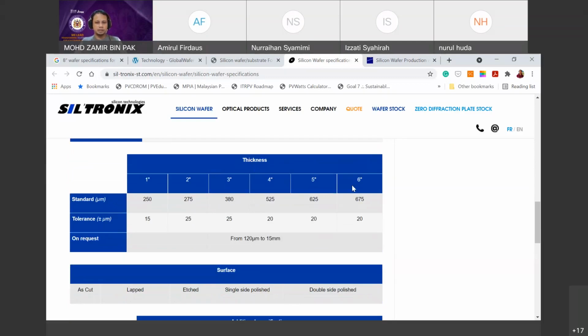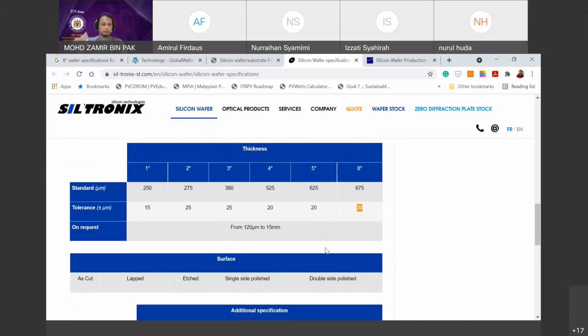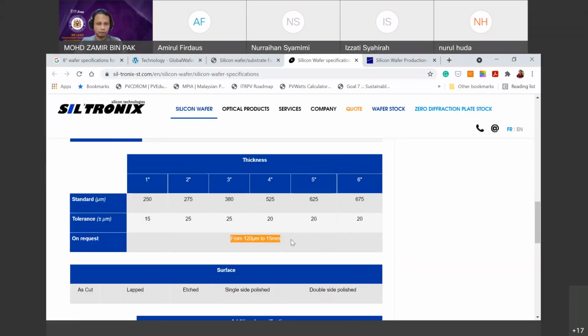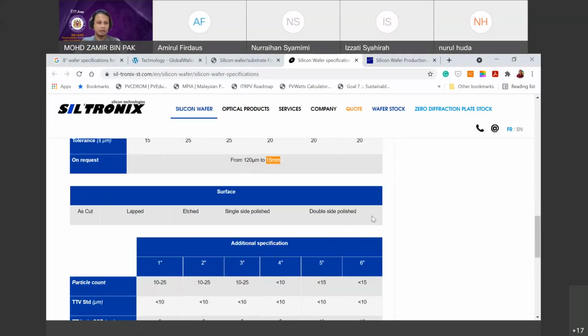Say, for example, if you want to use 6 inch, so that means they are offering 675 micron wafer plus minus 20 micron. Okay. So ada juga on request if you want to have 120 micron up to 15 mm pun ada. So that means very, very thin. Very, very thick, sorry. 1.5 cm ataupun 15 mm. So that's relatively thick for a silicon wafer.